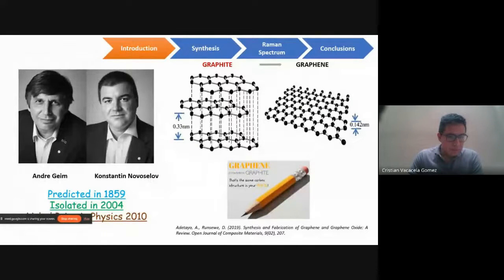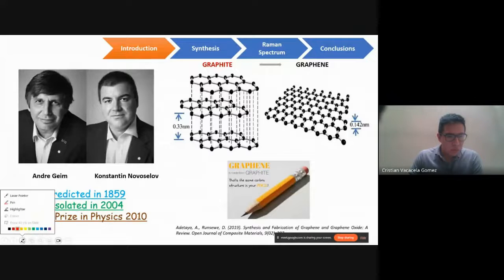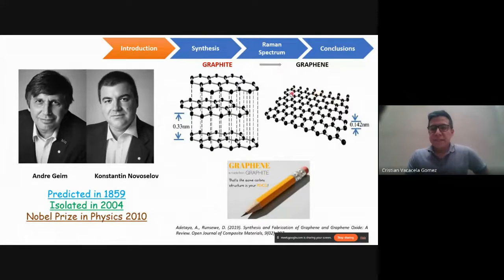Let me activate the laser. Okay, you can see here is my graphene. This is a carbon structure, a honeycomb-like structure where the carbon atoms are 0.142 nanometers apart, and the interaction distance between planes in graphite is around 0.33 nanometers.